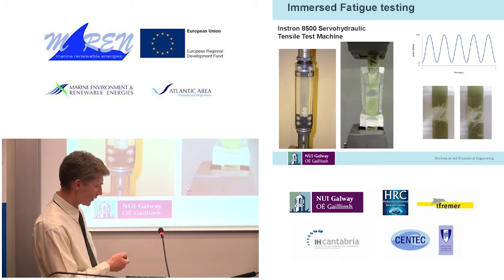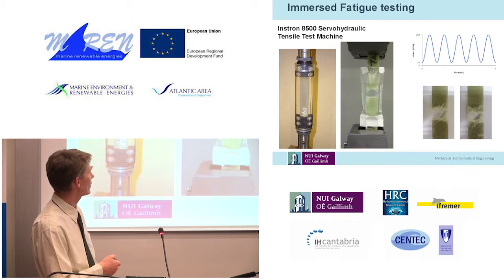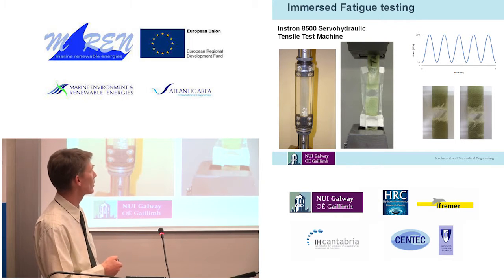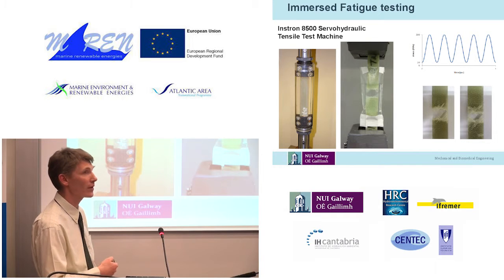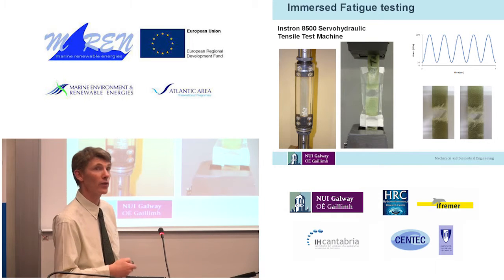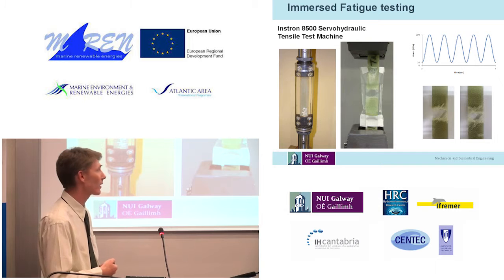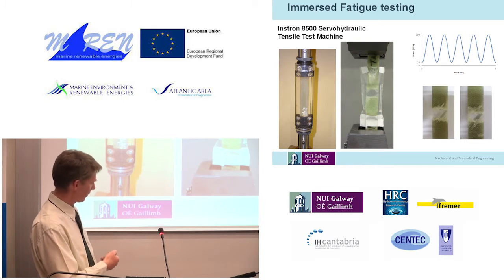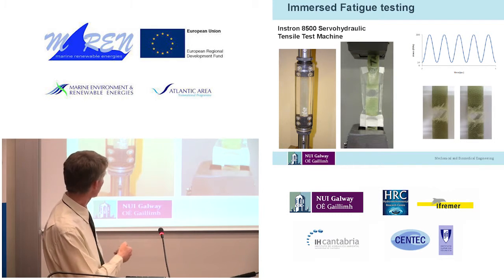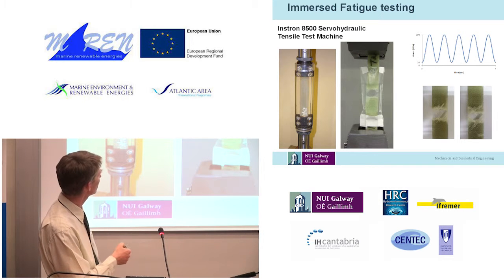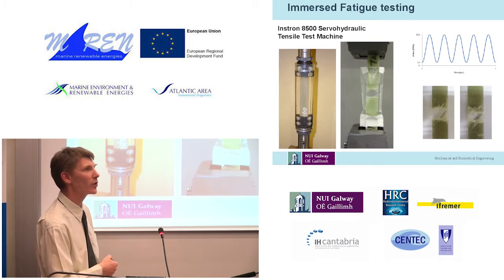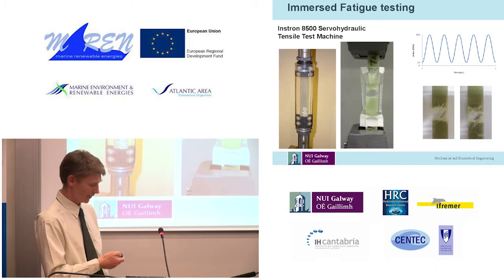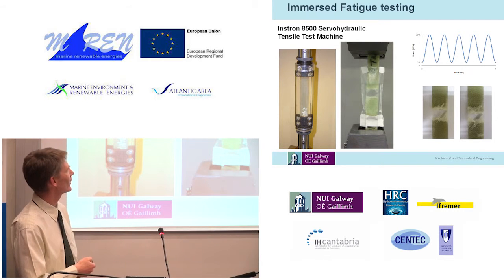One of the things we learned during this process was that it is important to keep the samples immersed while they're being tested, because otherwise they have a tendency to dry out, and as they dry out they regain their strength. So we came up with 2 different types. First of all, I started out with this nice looking but slightly complicated setup, and eventually I found that this nice simple plastic bag and some waterproof tape worked just as well. So that's what research is, I suppose.